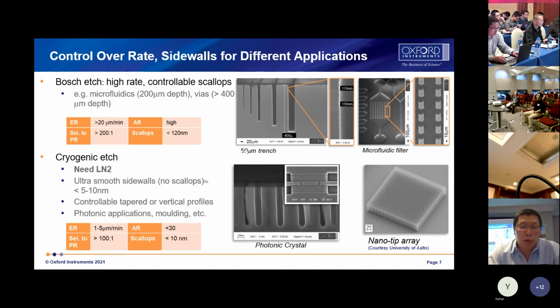The Bosch process gives a high rate, so it's suitable for etching micro-scale devices, and smooth sidewalls utilizing our fast switching capabilities. In real device fabrication, we usually trade off etch rate and selectivity for enhancing high aspect ratio and smooth sidewalls.